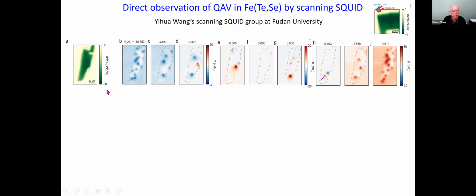I'm just going to briefly flash these data. This is the diamagnetic susceptibility. You see the sample, which is a FeTeSe flake. And then here, the SQUID coil will pick up the magnetic flux. The center three are zero field cooled, and they have to do a lot of experiments to make sure there are no magnetic fields around. And you see different zero field cooling will give you these vortex anti-vortex pairs in zero magnetic field.